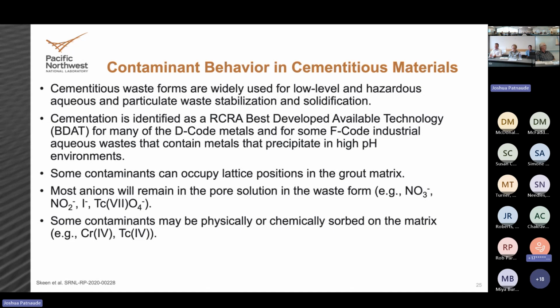So if you remember from the start, that fundamental chemistry, one of the products that we make is calcium hydroxide. That makes a high pH environment that stabilizes the calcium silicate hydrate. Well, high pHs also lead to precipitation of many of the hazardous metals. And if they precipitate down from a soluble state to an insoluble state, they're not mobile, they're contained within the waste form.